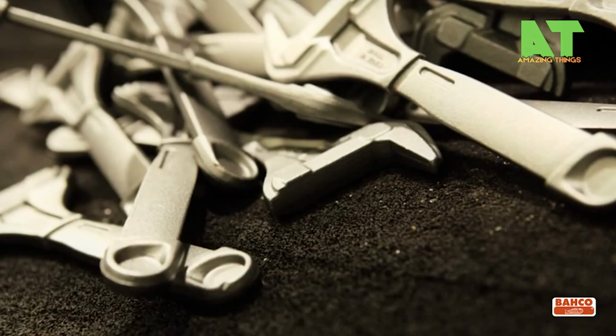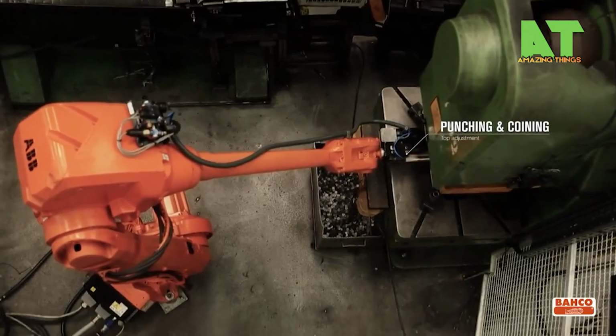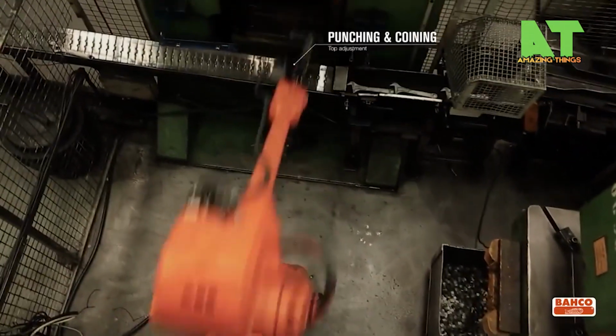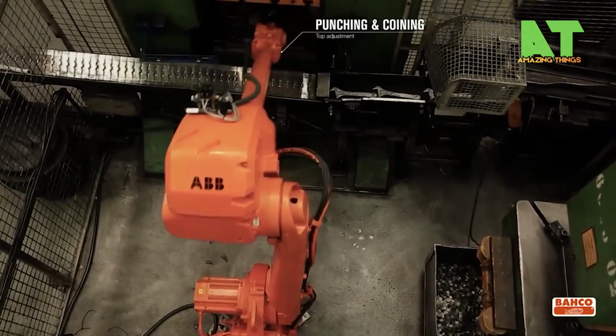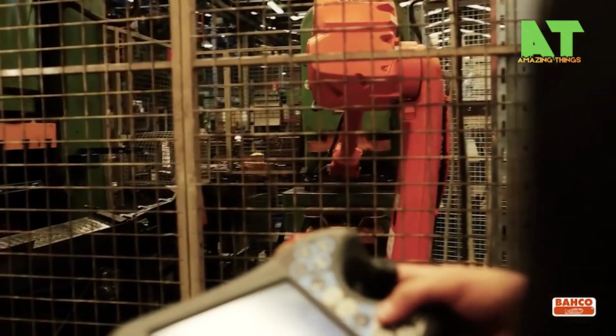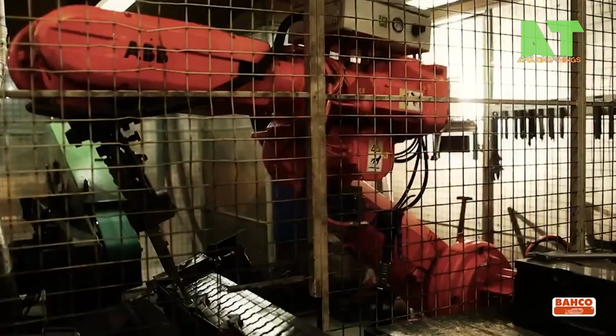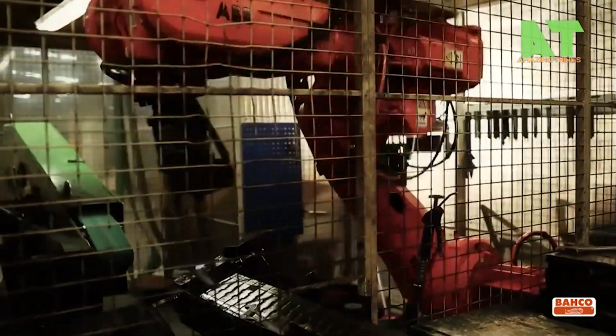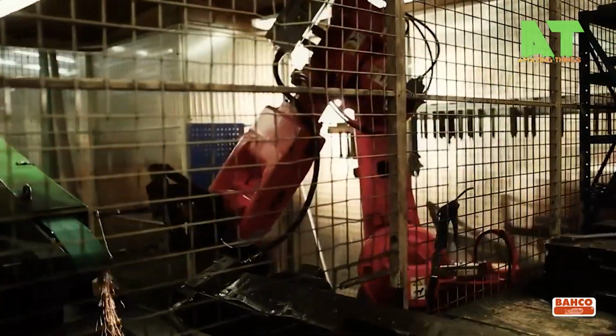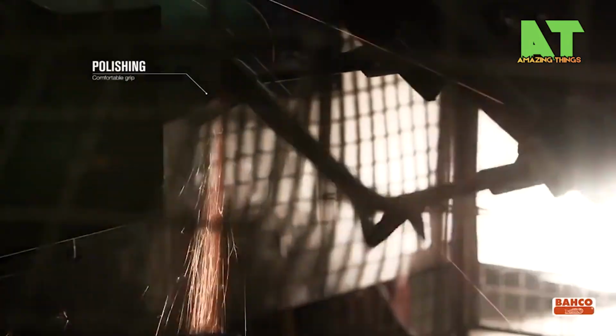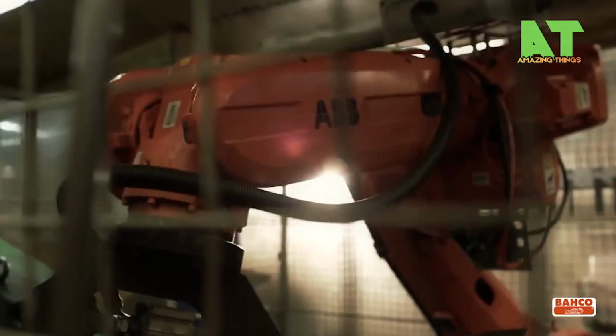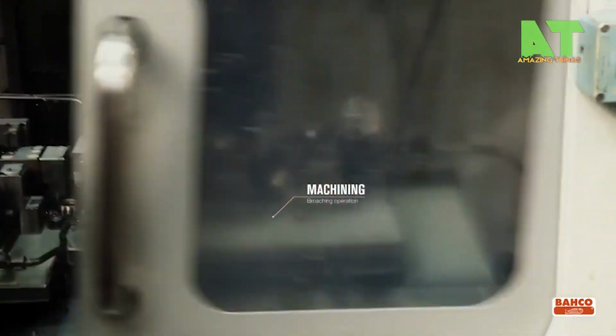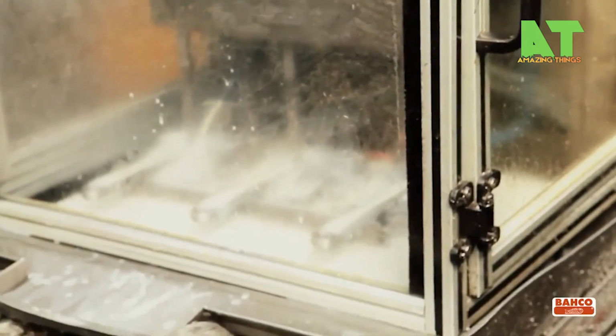Those billets go into a powerful drop forge press, where intense heat around 1200 degrees Celsius makes the steel malleable. The press then strikes with thousands of pounds of force, shaping the rough wrench body in just a few blows. This forging process aligns the grain structure of the steel, making it significantly stronger than a cast piece ever could be. After forging, the wrench heads through a CNC milling station, where the jaw surfaces, the worm gear channel, and